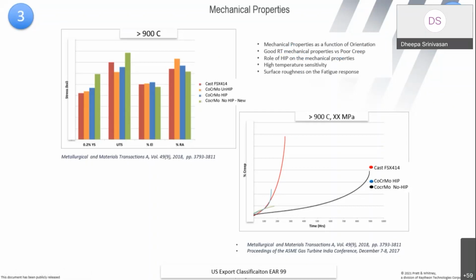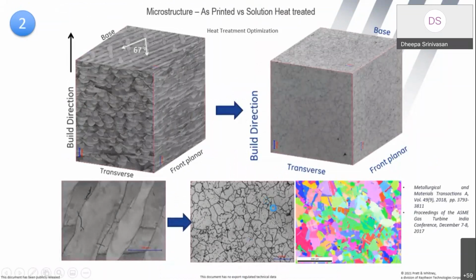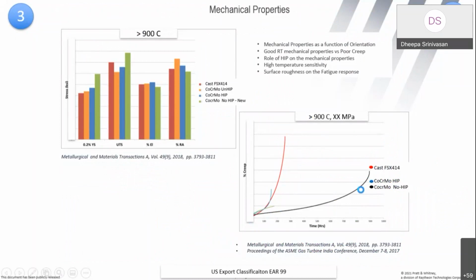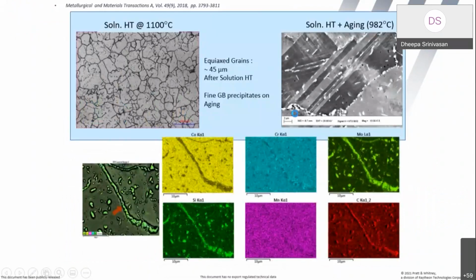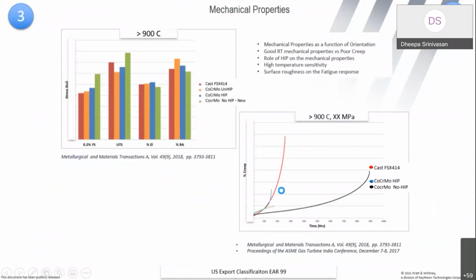So I'll again share an example of that. In our particular case, going back to the case study, we were lucky that despite having a fine grain structure, since it was isotropic, there's no problem. When we did the creep test along with the samples sent for various orientations, we were able to find that we had a very slow creeper in this particular cobalt chromoly without any hipping, the new material that we developed. Of course, can we stop there?